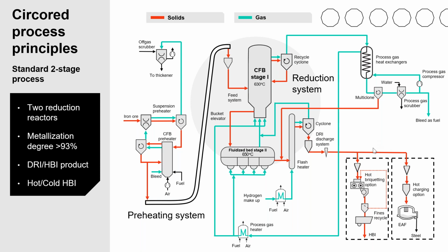The highly metallized DRI gets discharged from the second stage reactor and superheated by the flash heater to appropriate temperatures for hot briquetting to produce HBI, or alternatively, the material can be directly charged to an EAF for hot charging. We had mentioned the option for microgranulation, which is shown on the next slide.